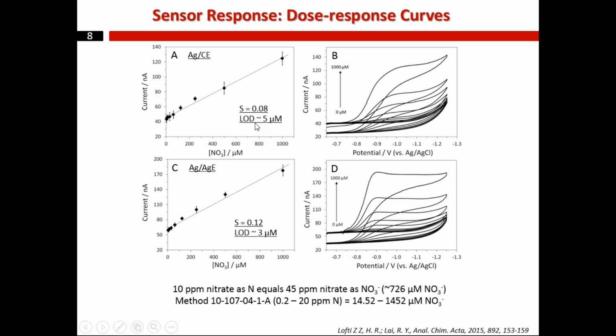As you can see, we could get the limit of detection of around 3 to 5 micromolar for both of the sensors. And if you think of the MCL, or the maximum contamination level of the nitrate, which is 10 ppm as N in nitrate, which is almost equal to 726 micromolar of nitrate, you can say that this value is within the linear range of the sensor. Therefore, this sensor can be used for detection of nitrate. Furthermore, the linear range of this sensor is comparable to the EPA approved method. Therefore, you can say that this method can be used as an alternative method for detection of concentration of nitrates.